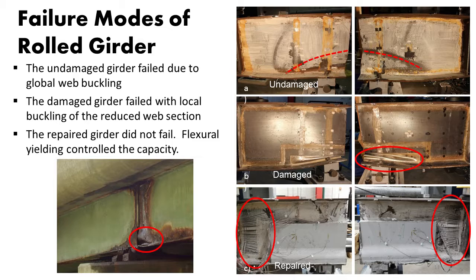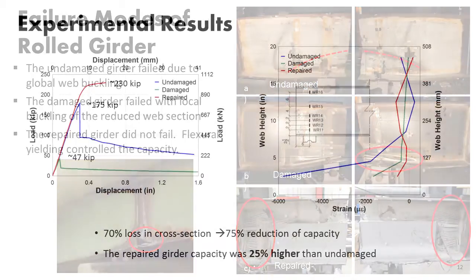And this is the repaired one. These are UHPC casts, the two sides of the specimen. And we actually were not able to fail it, not because of the capacity of the load frame, but because we reached the moment capacity, or flexural capacity, of the beam. So essentially, it's good for capacity design because it can utilize the entire flexural capacity of the beam and take the shear or bearing failure out of the picture. What we observed is very comparable with what you see on site if you have extensive section reduction.